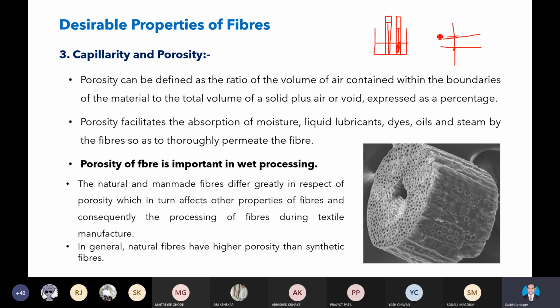Now in case of the synthetic fiber also, we can increase this property, porosity, by doing modification during the spinning stage. We can manufacture hydrophilic polyester, hydrophilic nylon, and hydrophilic acrylic fiber, so that the moisture level can be increased. In case of polyester, the moisture is in the range of around 0.4%. But if you manufacture the hydrophilic polyester, the moisture level can go up to 6 to 8%, just like cotton.